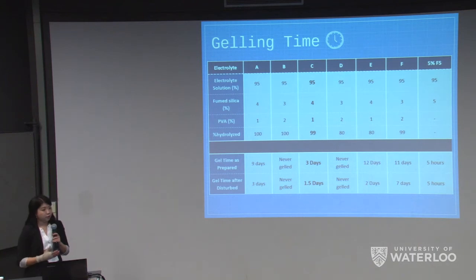So when we were designing our gels, several additives were made into a solution as an additive to the original liquid electrolyte. The addition that we had was only about 5% throughout all of our tests, varying in the ratios of fumed silica and PVA between 4 and 3 and 1 and 2 respectively. And also with the PVA used, we had different hydrolysis percentages that ranged from 80 to 99 to 100. And one of the purposes of PVA was to enhance the dispersion of the additive in the electrolyte.